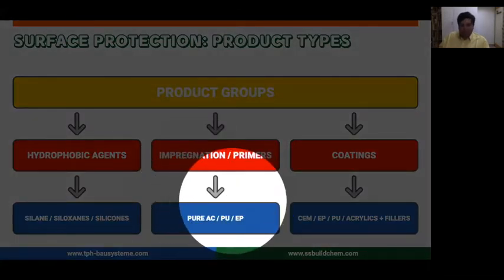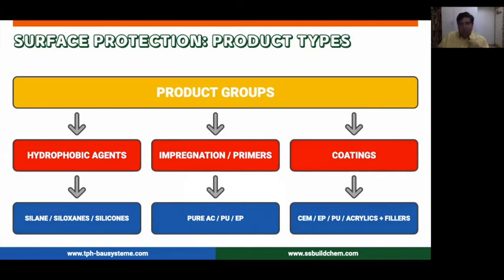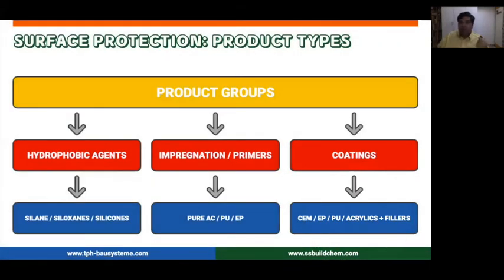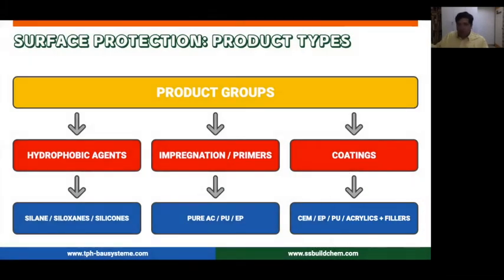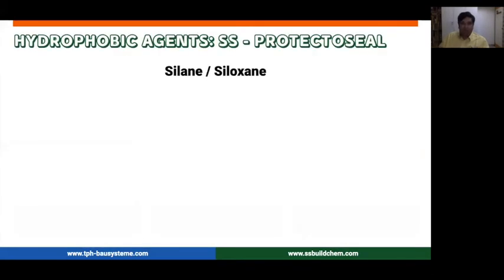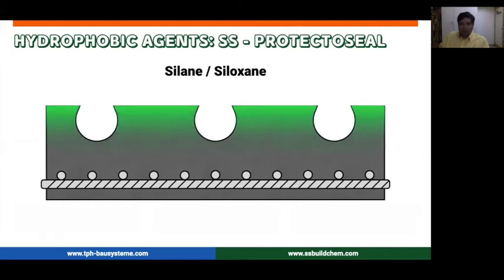So these are basically pure resins. That means pure acrylics, pure PUs, pure epoxies. Then they act as your impregnation primers. And finally, you have the coating systems, which can be based on cement, epoxies, polyurethanes, acrylics, but they're all basically filled systems. That means it will be these pure resins along with fillers, so you can have a coating and it protects your structure in the long run. So your basic silane siloxane system, it's a hydrophobic agent. So as soon as you apply it, it just comes down through your concrete, enters it and protects it against the ingress of water. Very simple mechanism.